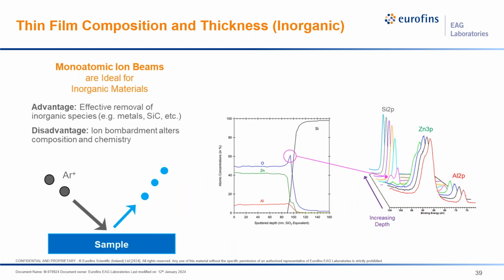We can couple that with an argon beam, monoatomic ion beams, and these are ideally suited for depth profiling of inorganic materials. And here's an example where we can look at sort of a montage plot of the same sputter depth profile, where you can actually see the chemical state as we go through the profiling through the material. So you can see where we hit the interface between the aluminum oxide, silicon oxide, and the silicon substrate. In all cases, these monatomic ion beams are fairly destructive, so we have a tendency to reduce or destroy the chemistry as we sputter down through it.